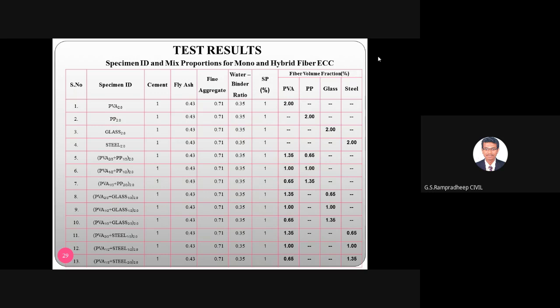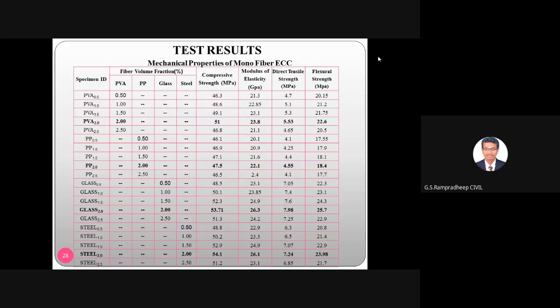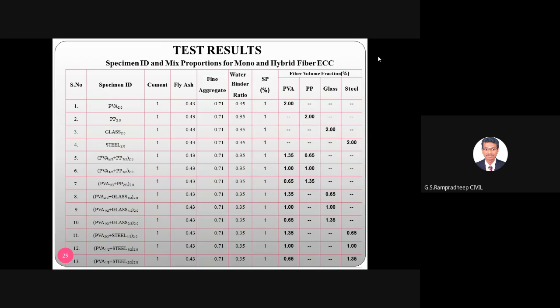He is taking the PVA low modulus fiber as the best value, because from the previous results, the low modulus fiber gives 51 MPa. He is leaving that PP, right? So PVA, PP. Why is PVA, PP taken as the low modulus fiber grouping? PVA he is taking for 2/3, and PP for 1/3. So around 60 to 65 percent he is taking for PVA, and 33 percent for PP. Why is it so? We have to raise the question.